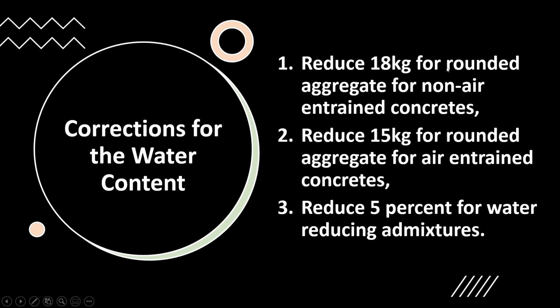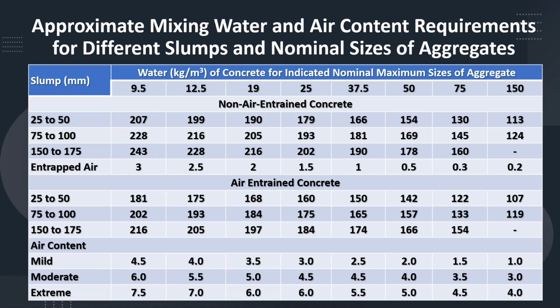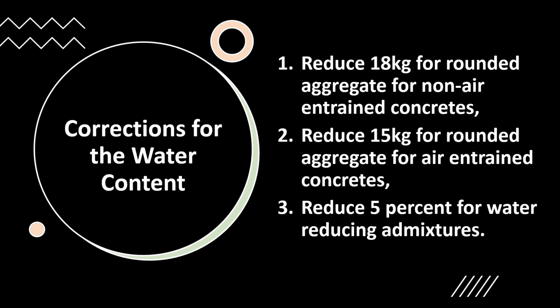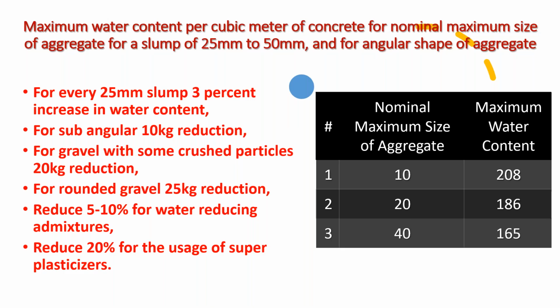So with certain modifications, certain approximations, we changed these values and brought them to our code. Of course, there are certain correction factors in the ACI code, and we have also adapted certain correction factors for different water-cement ratios, for different slumps, for different shapes of aggregate, and all those things. And also what the water content will be if we use superplasticizer and all those things. We have given certain correction factors.